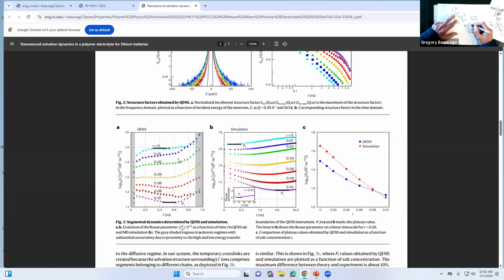And at -4, it comes down like that. And then it goes -4 again like that. But if you have persistence in here, like -1, then this thing will go up and then down again or something like that. And then people will look at this thing, and literally they will take that peak to have a meaning of size, and they'll take the width of it to mean something. So this kind of plot is kind of messed up. There should be a peak in your original data if there's a peak in the data. Generating it isn't really a good way to get it. So anyway, that's something to keep in mind.